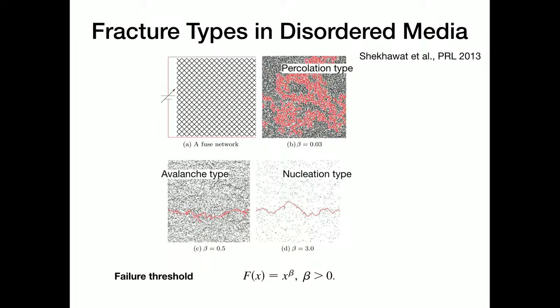My point is that instead of putting in disorder by hand like this, we also know that a fracture propagates at the tip of the fracture, where the stress is concentrated, and that itself acts as a propelling force to dispel the stress till the fracture opens. That's the Griffith criteria. So what I was trying to say is that this nucleation type and the percolation type are tuned basically by the way you are putting in the resistors. But if you had allowed a natural fracture to happen, just by driving it by the stress that accumulates, could we have differentiated in such clear categories? That is what I was wondering. This is percolation type, this is avalanche, or is this only a toy model?